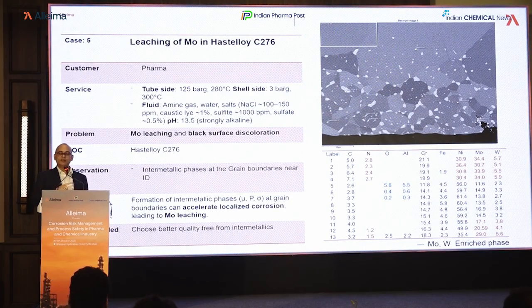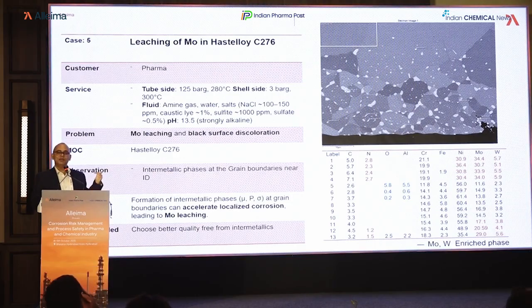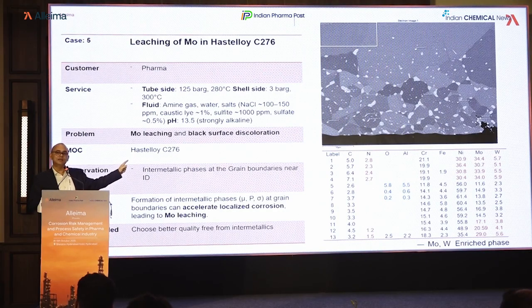So despite the very good grade, high-end grade, you may have problem if your quality is not good. So when we looked into the material, what we could see was that there were some intermetallics forming at the grain boundary. So this is basically related to your heat treatment issue. So when your heat treatment is not right, this can be the problem.